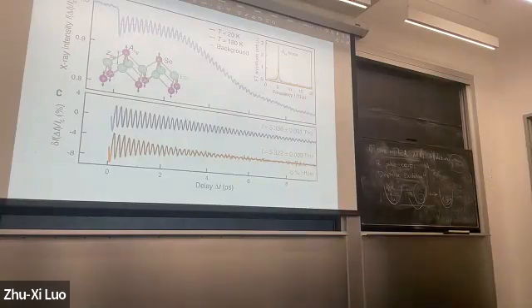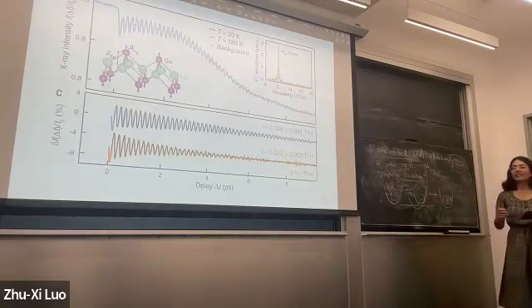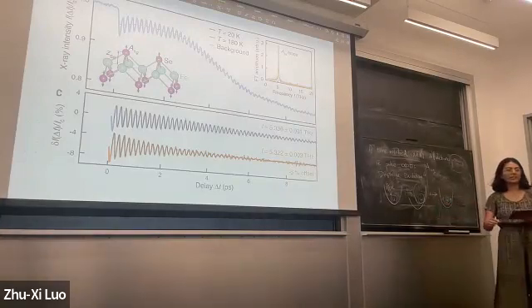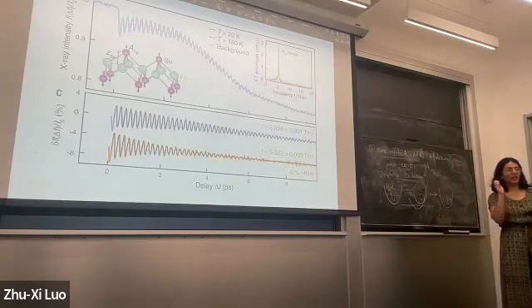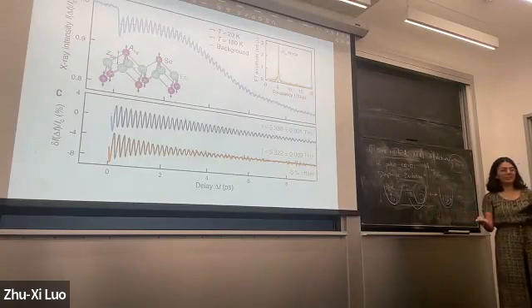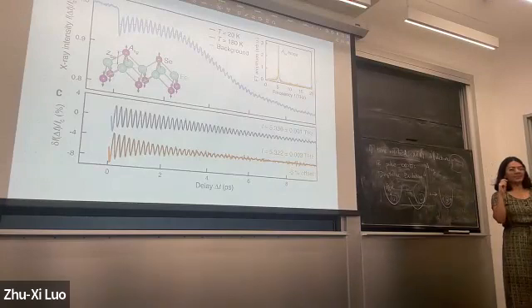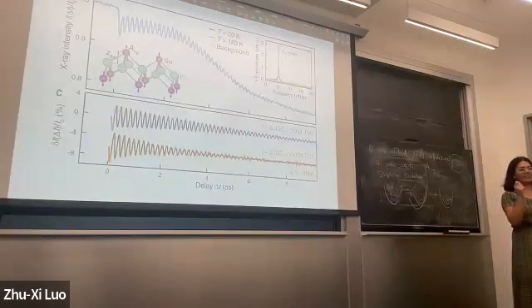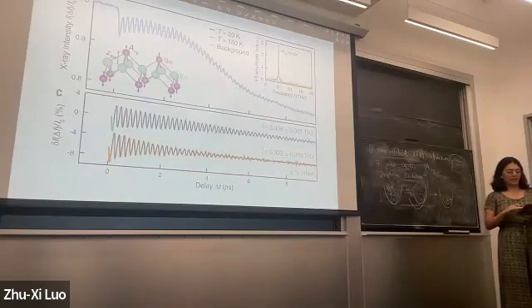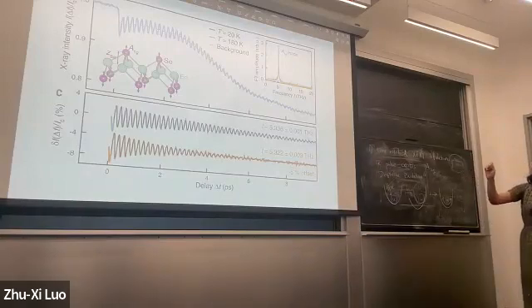Following this picture, what is shown also contains electronic contributions. So how do you separate out the electronic response from the phonon? Yeah, so the idea here is that the electron interactions are happening on a very, very fast time scale, even faster than this femtosecond resolution. And so going forwards, the dynamics that we will see will be due to electron-phonon interactions. And further, we'll see that the electron degree of freedom will also be oscillating at a frequency that's sort of locked with the frequency of this phonon mode.